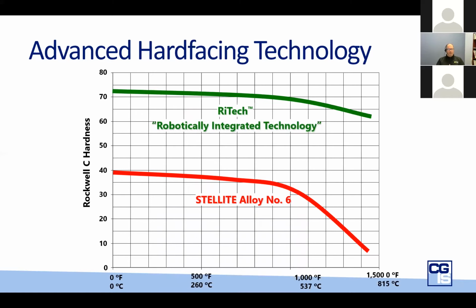So when we start talking about metal-seated valves, we need to realize that metal-seated valves are not created equally. There's a variety of different coatings that are utilized by manufacturers. We have to quite often use dissimilar metals in order to ensure that we don't have any cold welding or galling or marring. But with hard coatings, we can now look at thermal sprays using tungsten carbide or chrome carbide, which start off with a very high hardness and maintain that at elevated temperatures. So we can see with stellite, we lose our hardness as the temperature ramps up, and that also holds true for electroless nickel plating. ENP does start off harder than stellite, but it still does suffer from temperature effects and softening and losing its hardness.